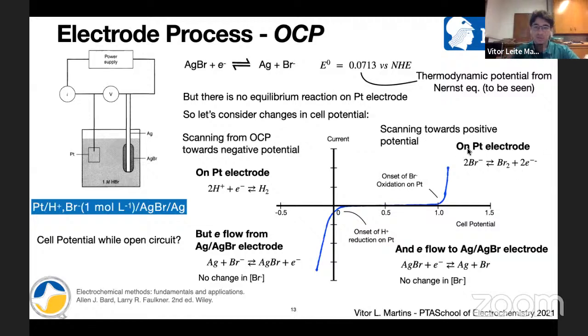and so the electrons need to flow to the other electrode now. So as bromide is oxidized, electrons are flowing to the other electrode, and then another reaction will occur in the silver-silver bromide electrode. That will be exactly the opposite reaction to what we had before, assuming again that there is no change in bromide concentration in solution. Okay, so now we have this curve here. You see no current increase in this potential window, and current increasing at those potentials, depending on what kind of reaction is occurring.